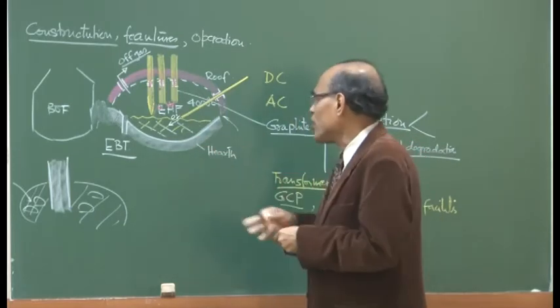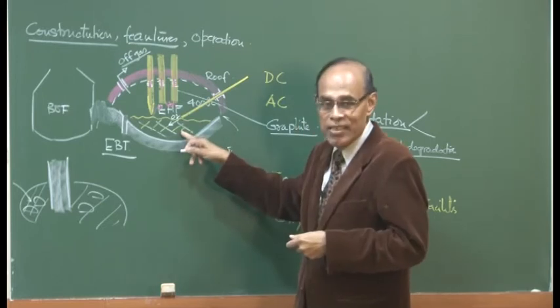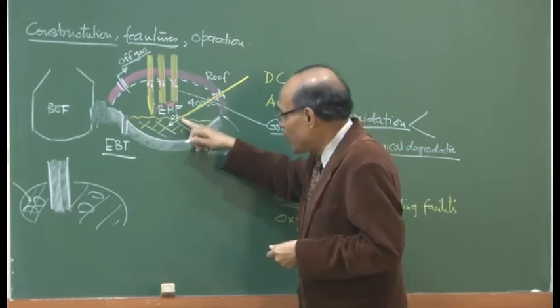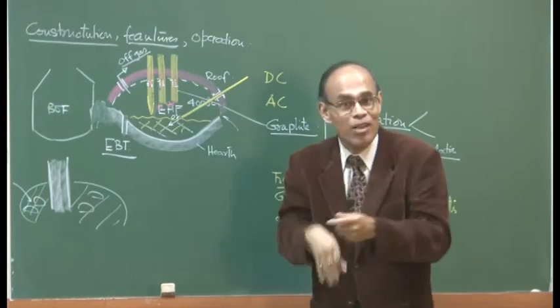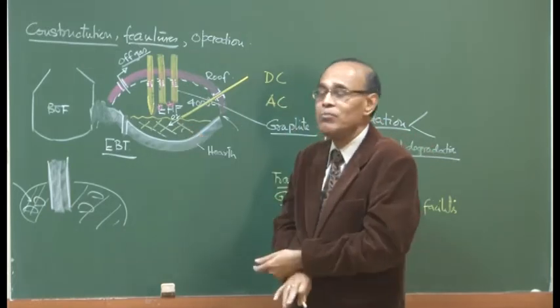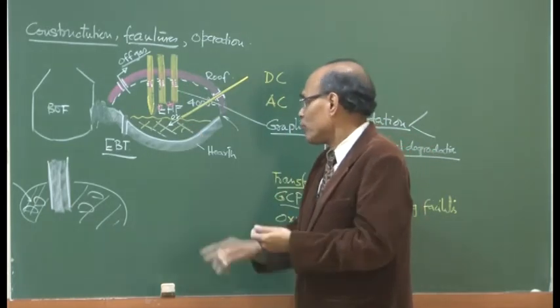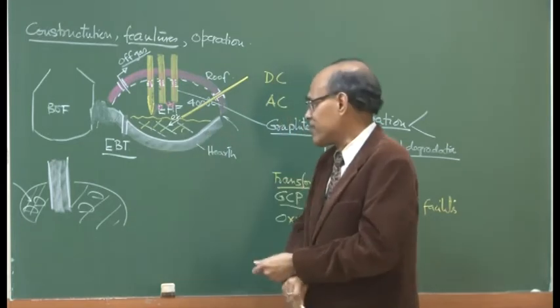Intermediate period, about 30-40 years back, oxygen lancing started, and this oxygen not only supplied the oxygen necessary for metalloid oxidation, but it also produced the necessary amount of stirring in the system itself.